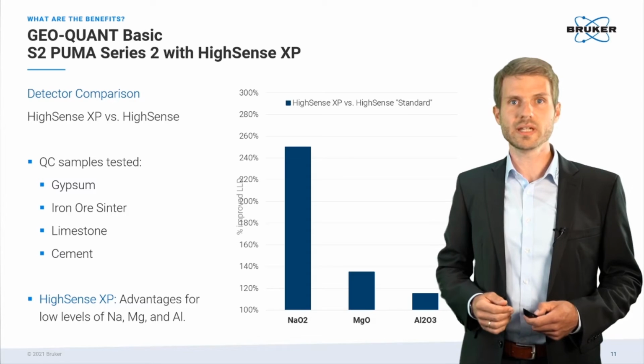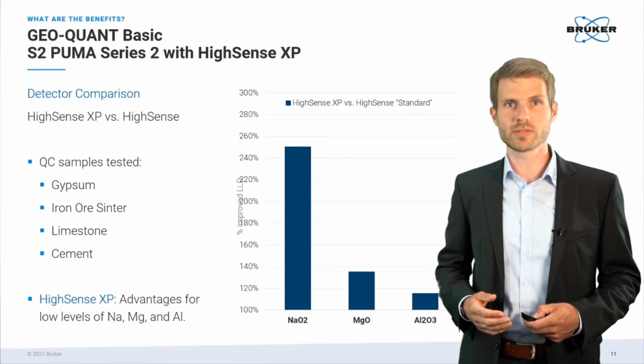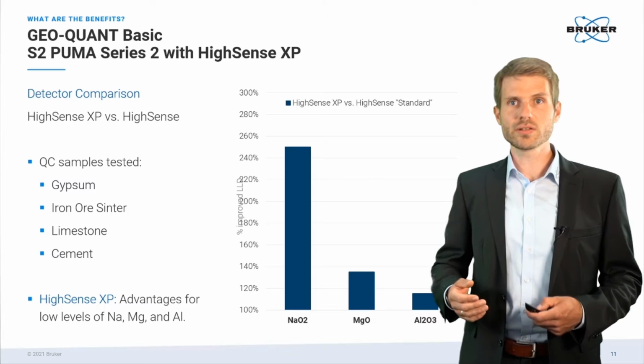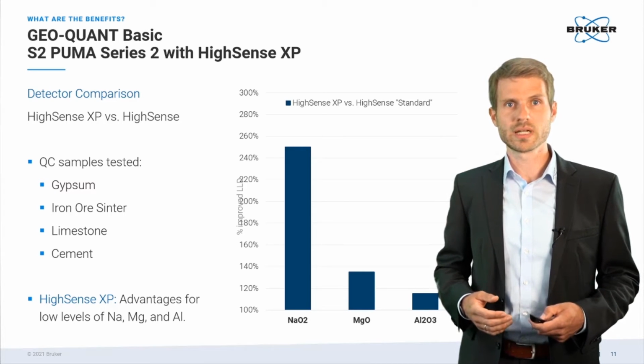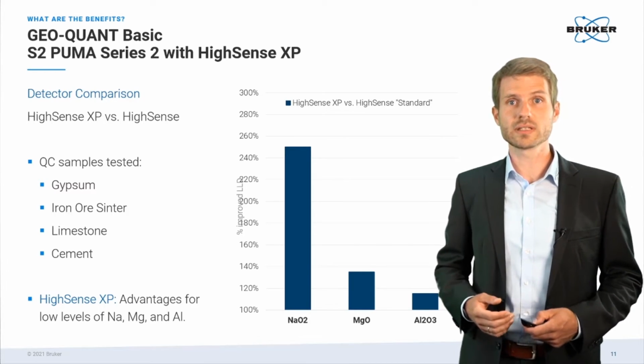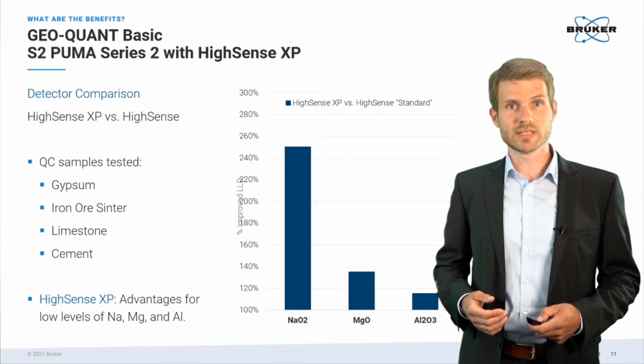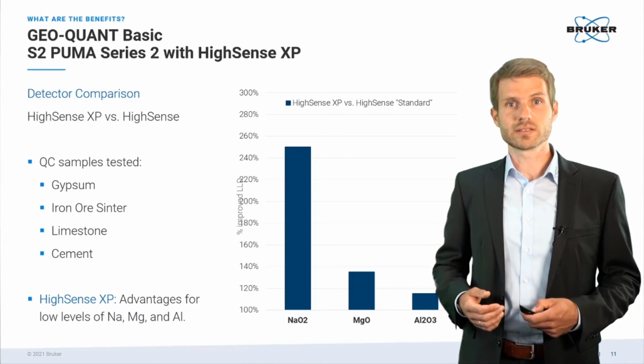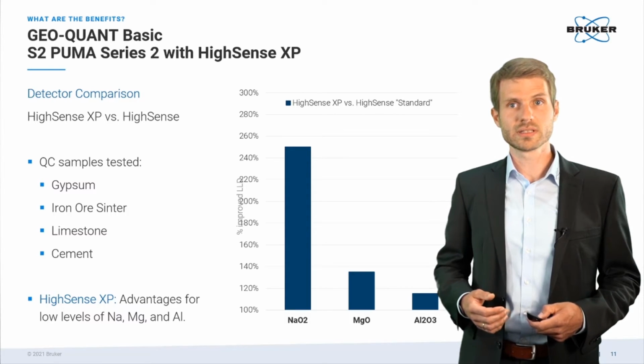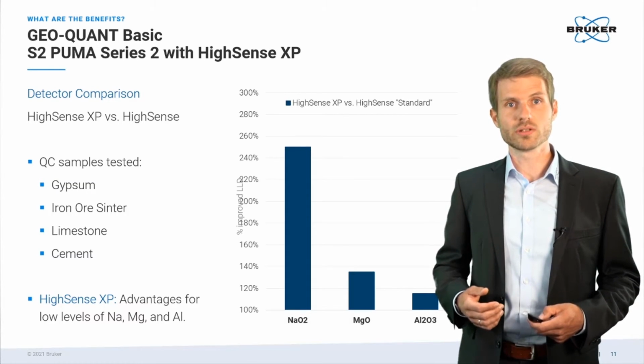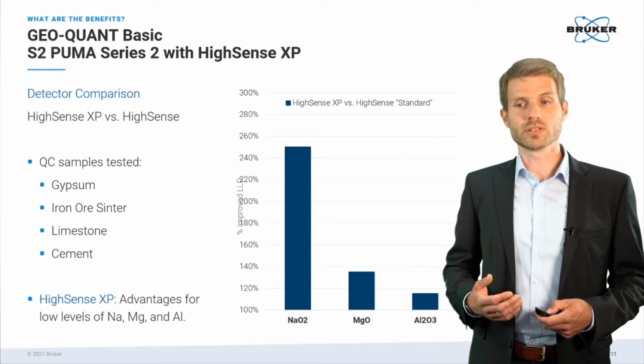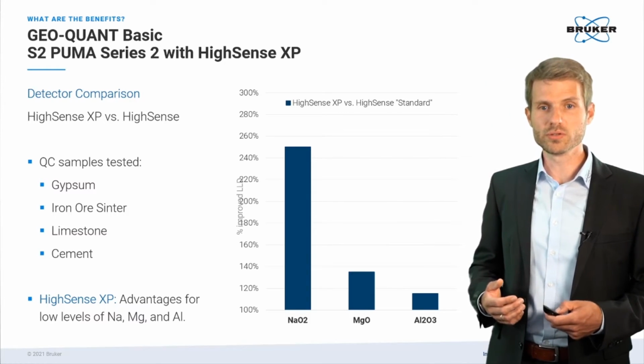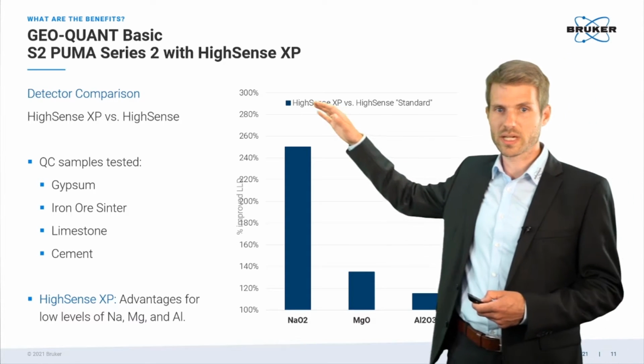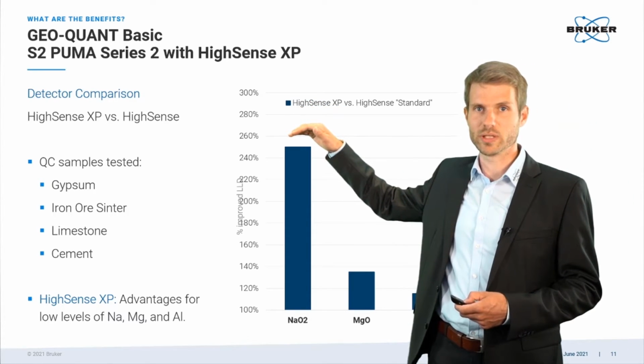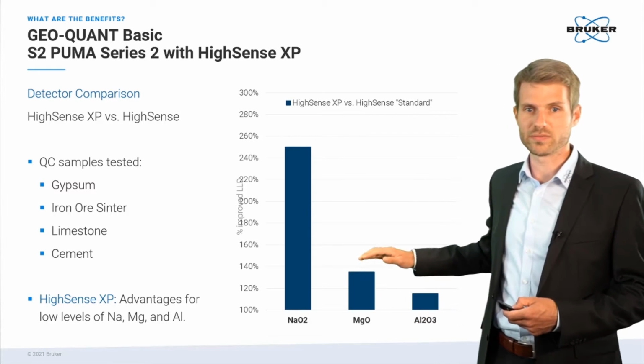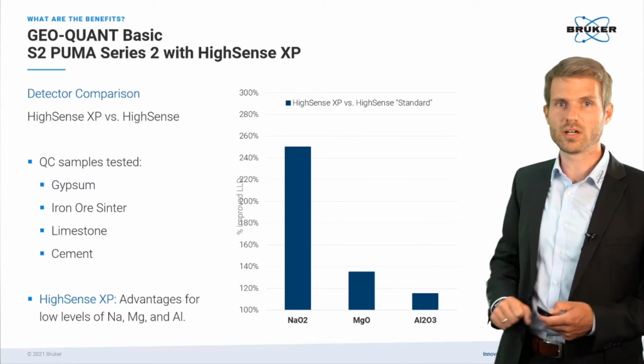Next, we performed a test comparing the lower limits of detection which can be achieved with the HighSense XP detector to the HighSense standard detector with beryllium window. As mentioned at the beginning, the XP offers clear benefits for light elements, and this results in a significant improvement for geological samples, as shown here for sodium, magnesium, and aluminum. Especially for sodium, the improvement of the lower limit of detection can be as high as 250%, while for aluminum, we still have an improvement of about 15%.